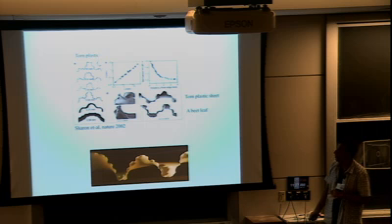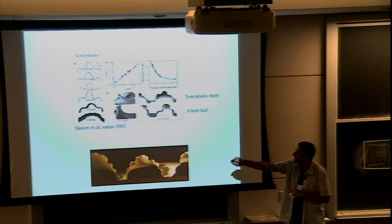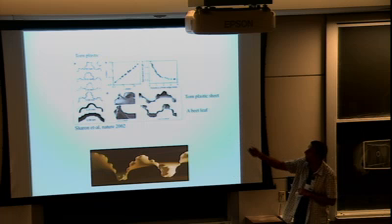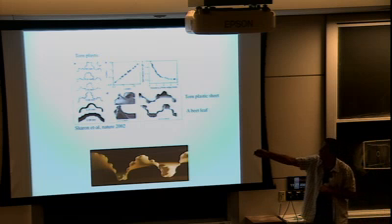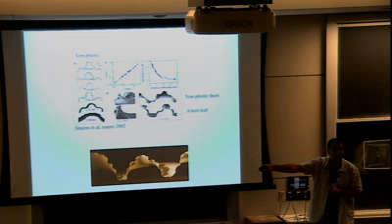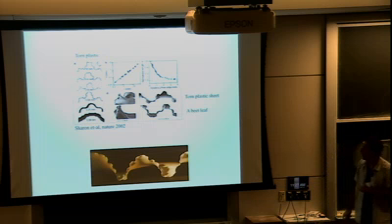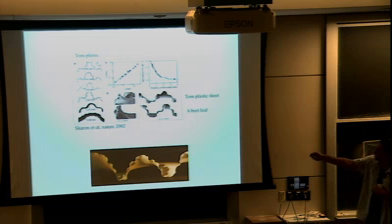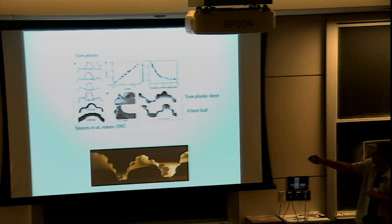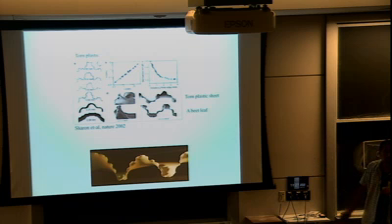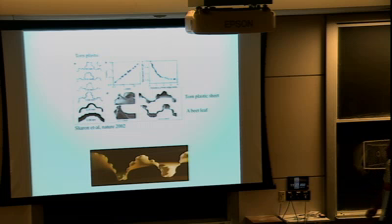If you do this very, very carefully, as done in this paper, and you tear something which is essentially 11 microns thick, this is kitchen saran wrap, you can get 6 generations of self-similarity of this shape. And I sometimes get these two mixed. I think I got it right here. But I think this one is a torn plastic sheet and this is a beet leaf, but it might just as well be the other way around.